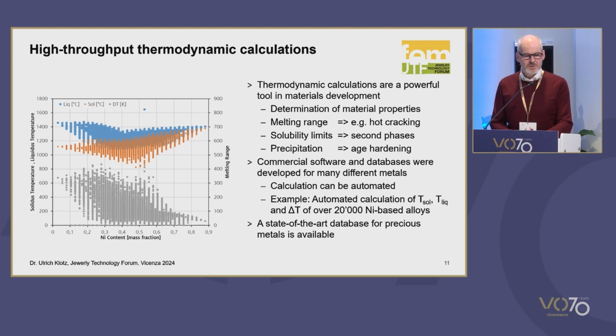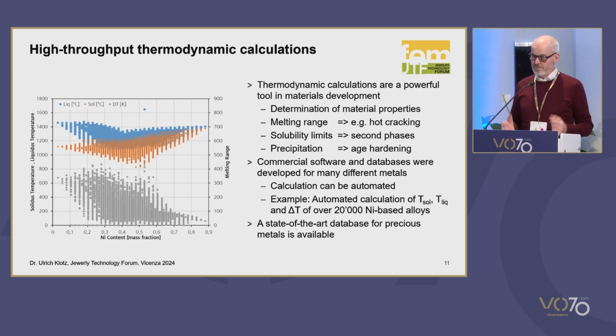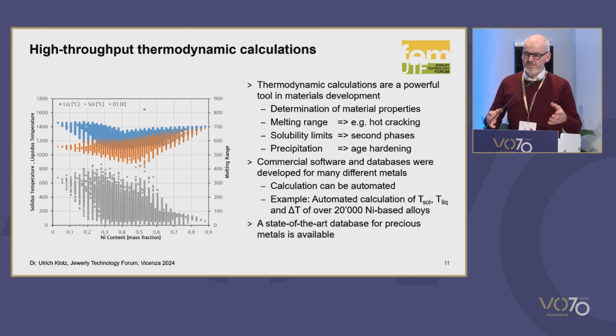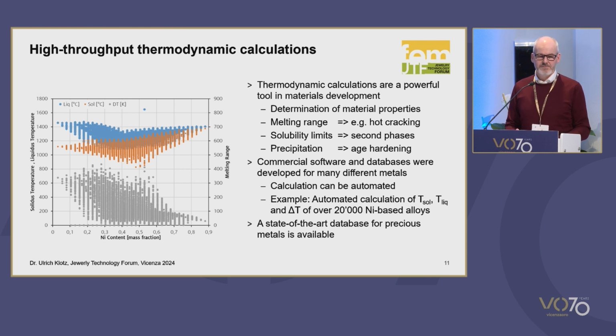Now we can also do the calculation of the solidus and the liquidus range, for instance. And this is an example I prepared for nickel-based alloys. These were alloys with up to 8 components based on nickel. And we wanted to vary the alloy compositions to find alloys with a suitable melting range, with a certain amount of phases.